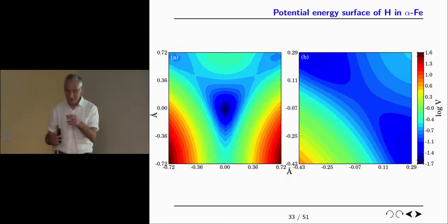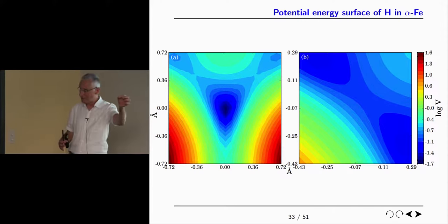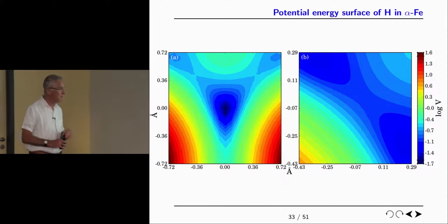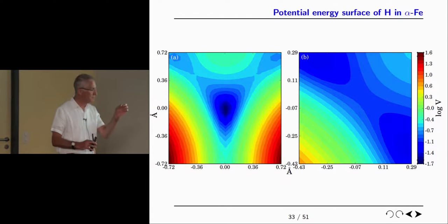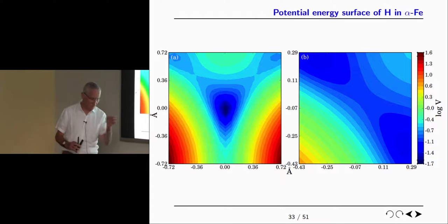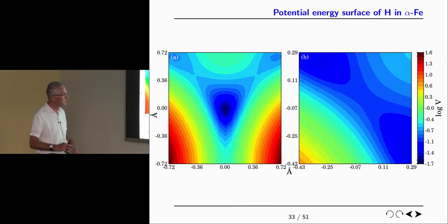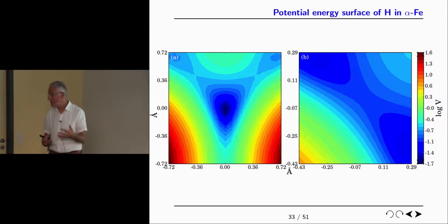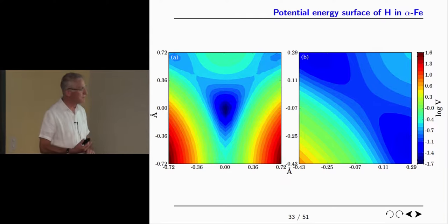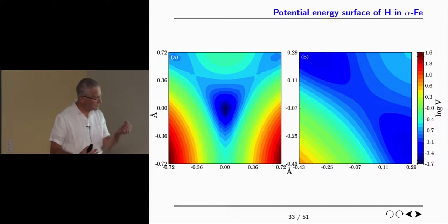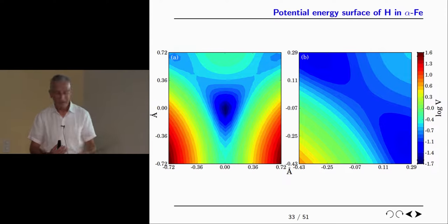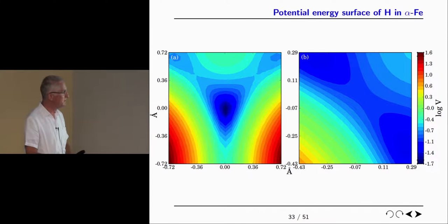And then we take the hydrogen atom, we move it to the saddle point, as I showed you, the saddle point in that adiabatic surface, the halfway position between the two tetrahedral sites. So he holds it in that position, and then again he relaxes the atoms around that, keeping the hydrogen at the saddle point, and then moving the hydrogen atom around in that fixed energy landscape, with those fixed iron atoms, you get an energy landscape looking like this. And we base everything on these two energy landscapes.